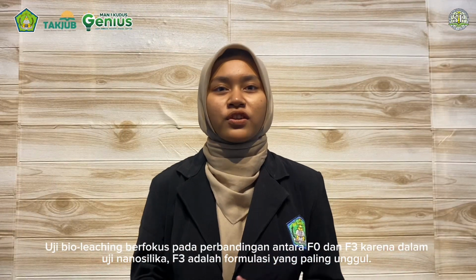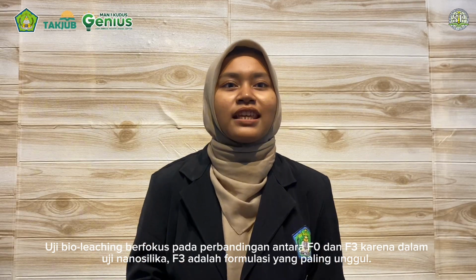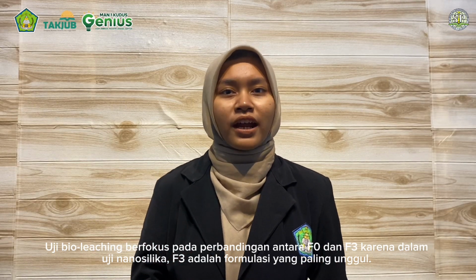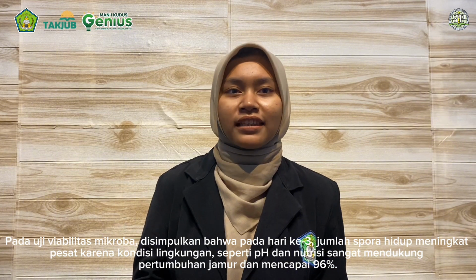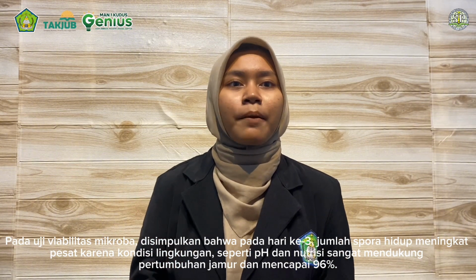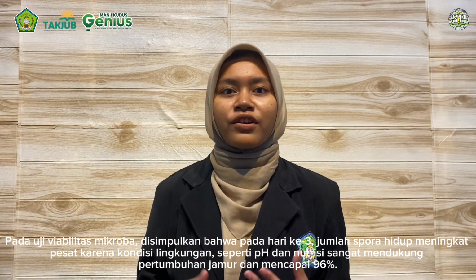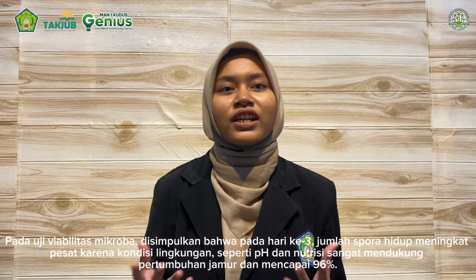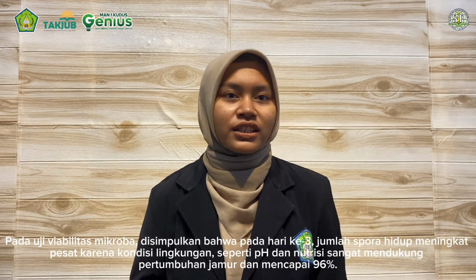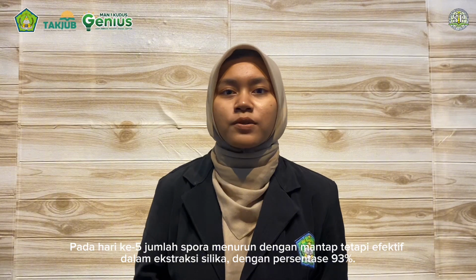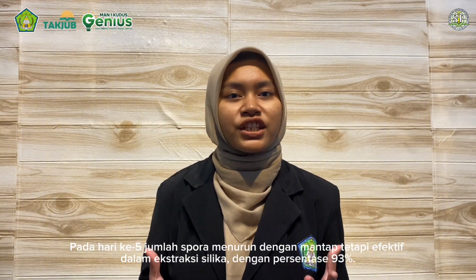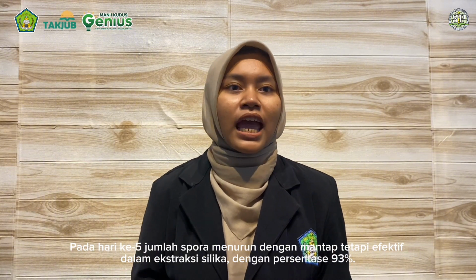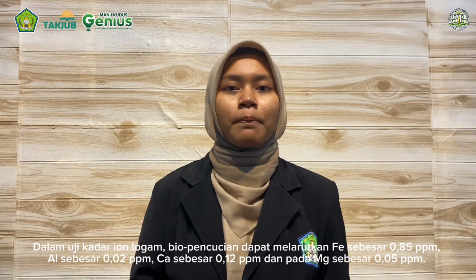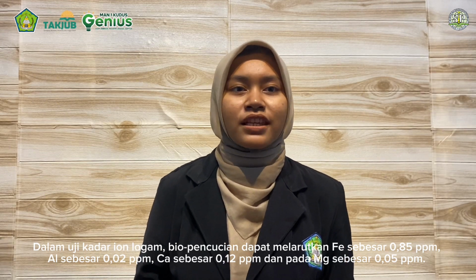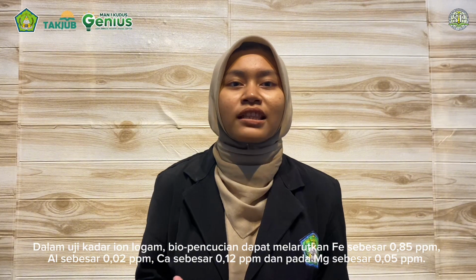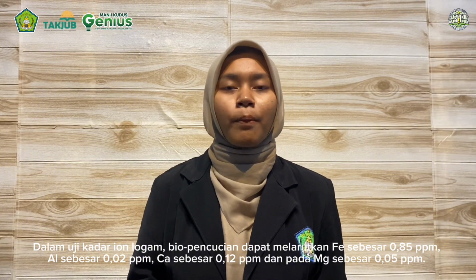The BioLeaching test focuses on the comparison between F0 and F3 because in the nanosilica test, F3 is the most superior formulation. In the microbial viability test, it was concluded that on the third day, the number of living spores increased rapidly because environmental conditions such as pH and nutrients greatly supported the growth of fungi and reached 96%. On the fifth day, the number of spores decreased greatly but was effective in silica extraction with a percentage of 93%. In the metal ion content test, BioLeaching can dissolve Fe by 0.85 ppm, Al by 0.02 ppm, Ca by 0.12 ppm, and Mg by 0.05 ppm.